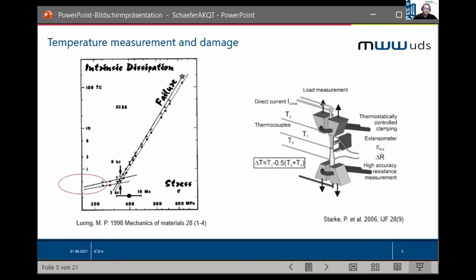One basic evaluation using thermography was done by Luong et al. They measured the temperature evolution in the middle of a sample in a stepwise load increase test, and they found that if the stress axis is logarithmic, you can see on the left-hand side, the temperature evolution has a knee point, and this knee point can be correlated with the fatigue strength regime. But measuring just the temperature is not the right way, because if the temperature would lead to failure, then all samples would break in the middle of the parallel length. And we all know this is not the case.